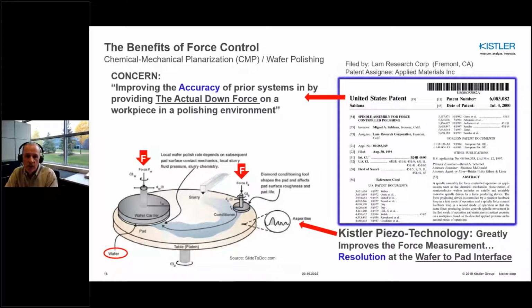Kistler dynamic force sensors provide improved measurement resolution, enabling one to sense the wafer to pad interface. I would also like to share the force sensor selected in this patent only had a fixed 500-pound range. The sensing technology within the sensor lacks scalability, and with it the ability to measure fine resolution. The force sensor had very good 0.1% accuracy, but it was locked in at 500 pounds. Hence, the resulting resolution was only a half a pound, unable to detect the fine pad to wafer interface aspects occurring within this process.